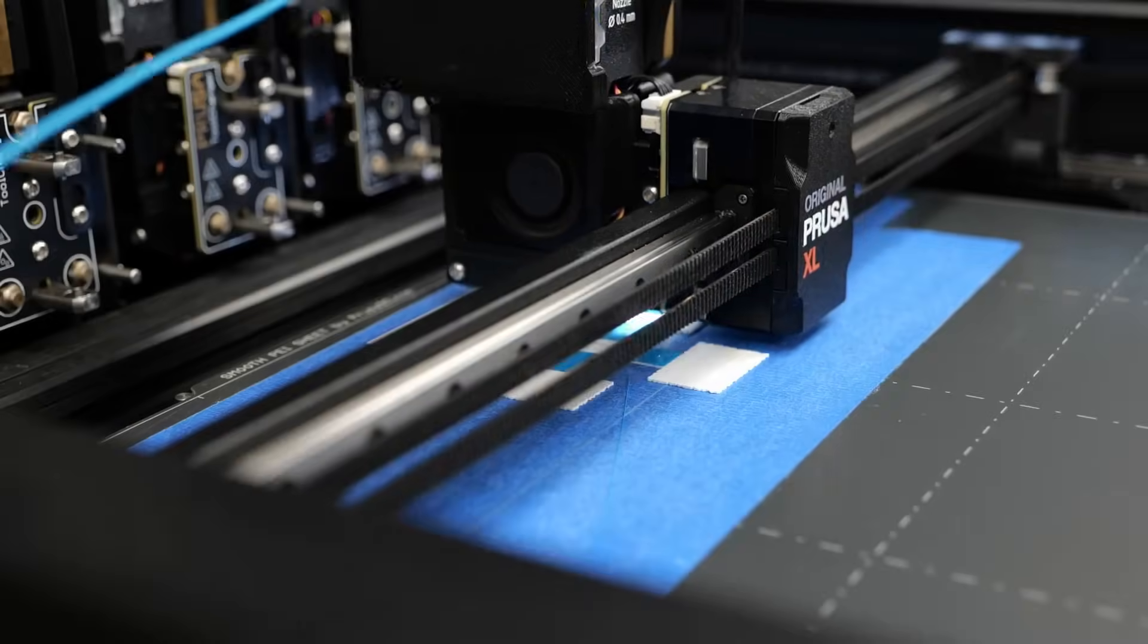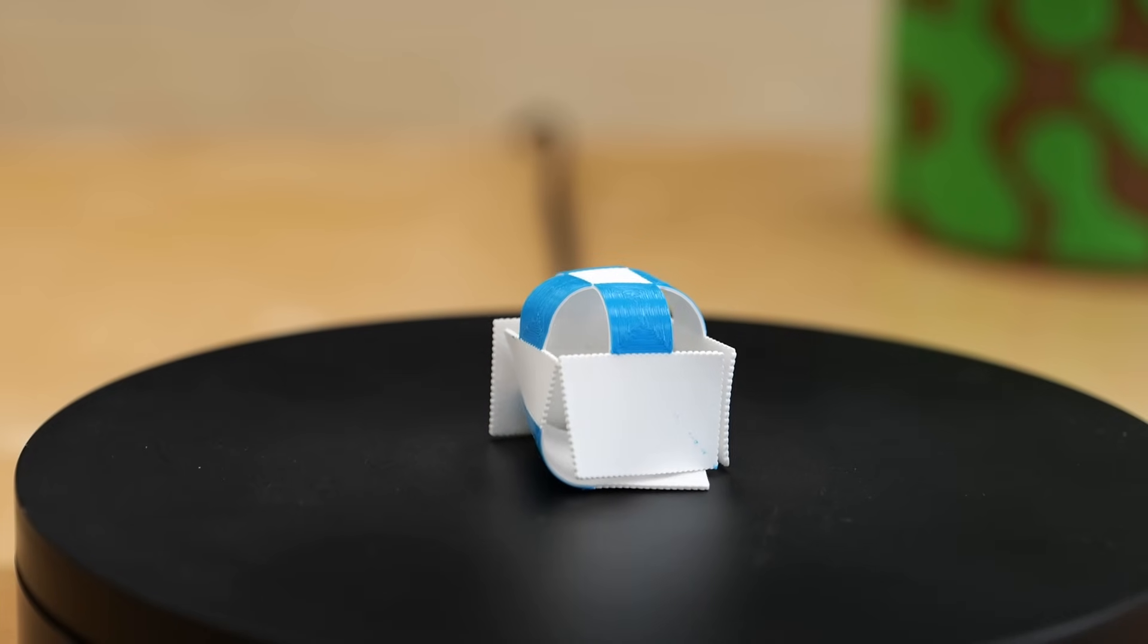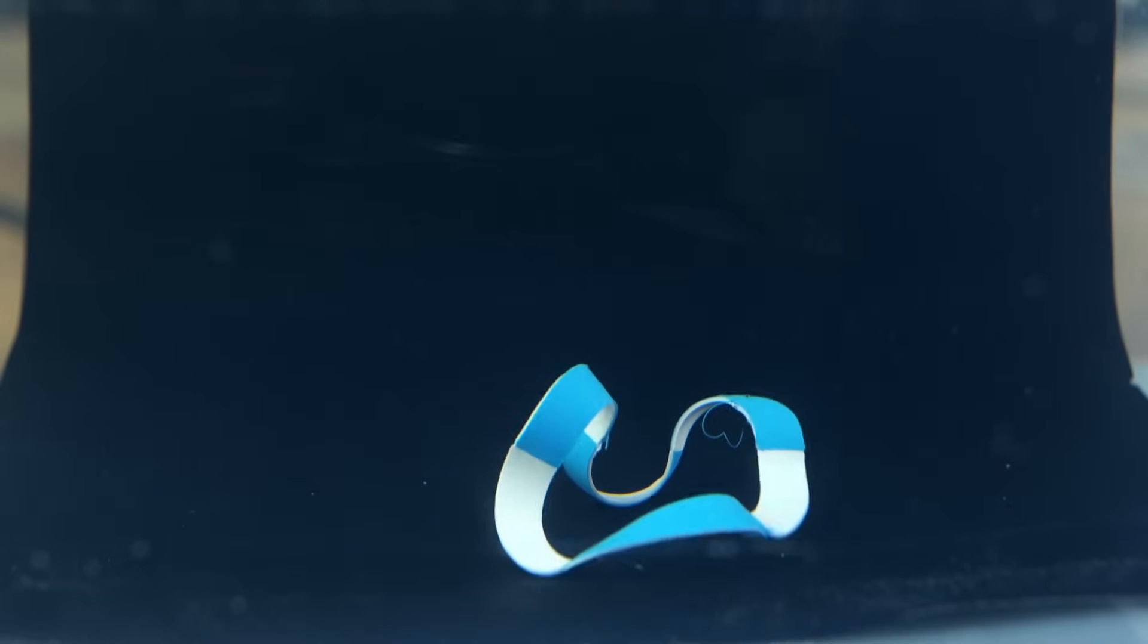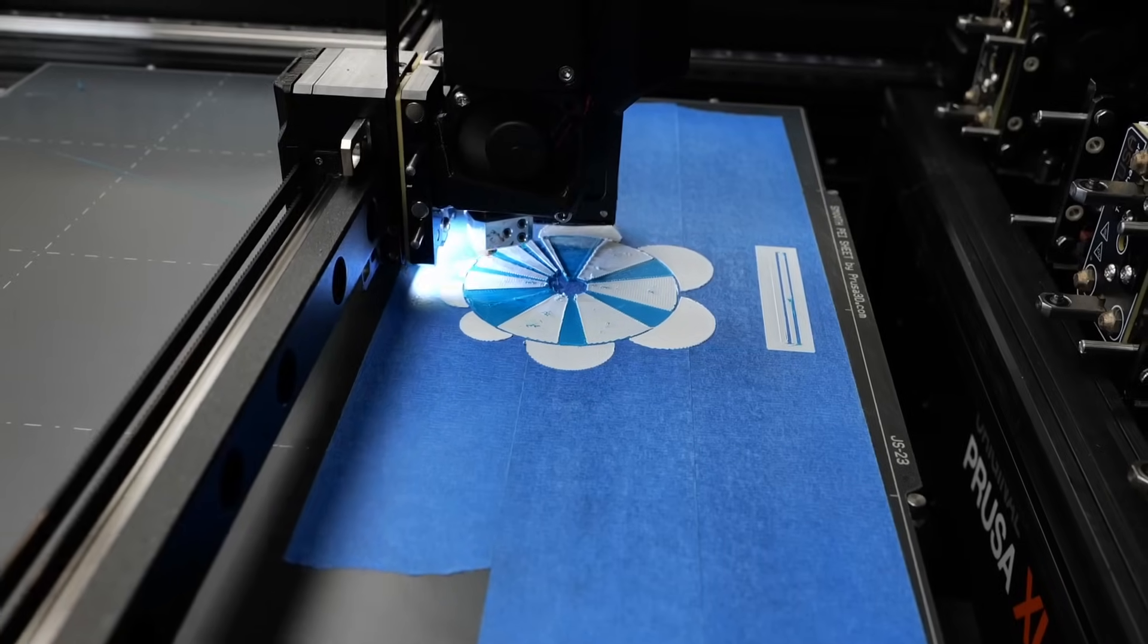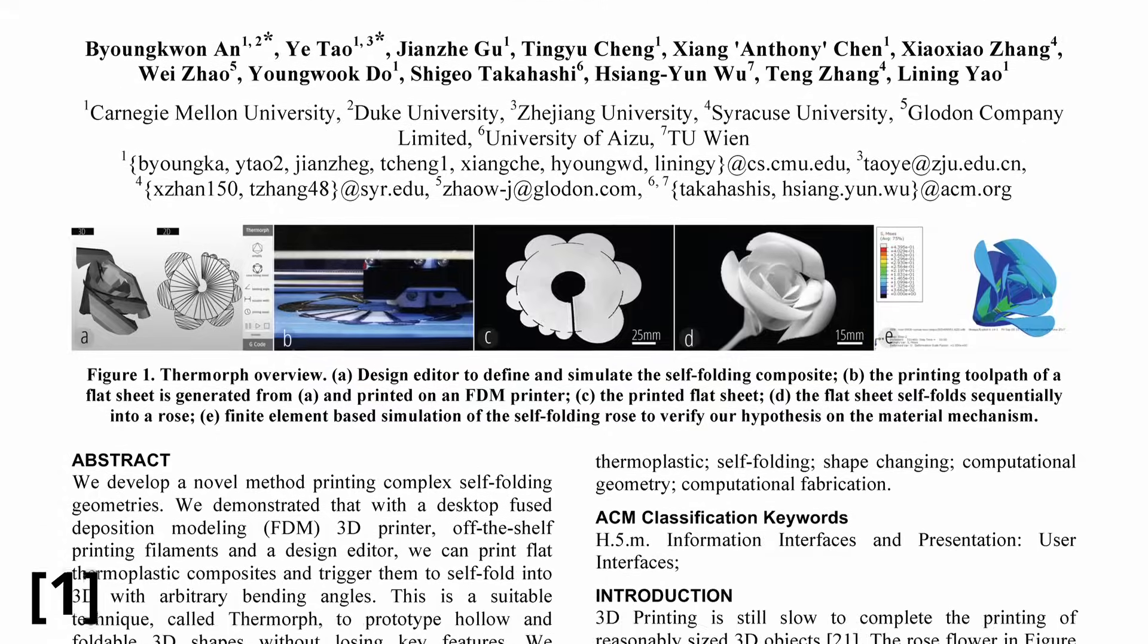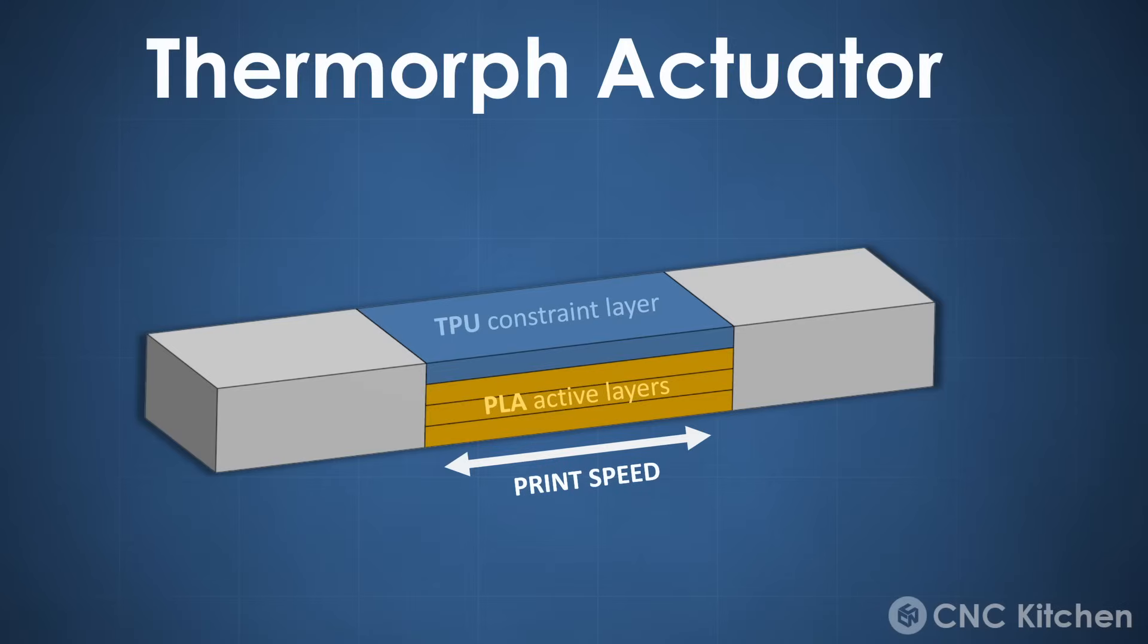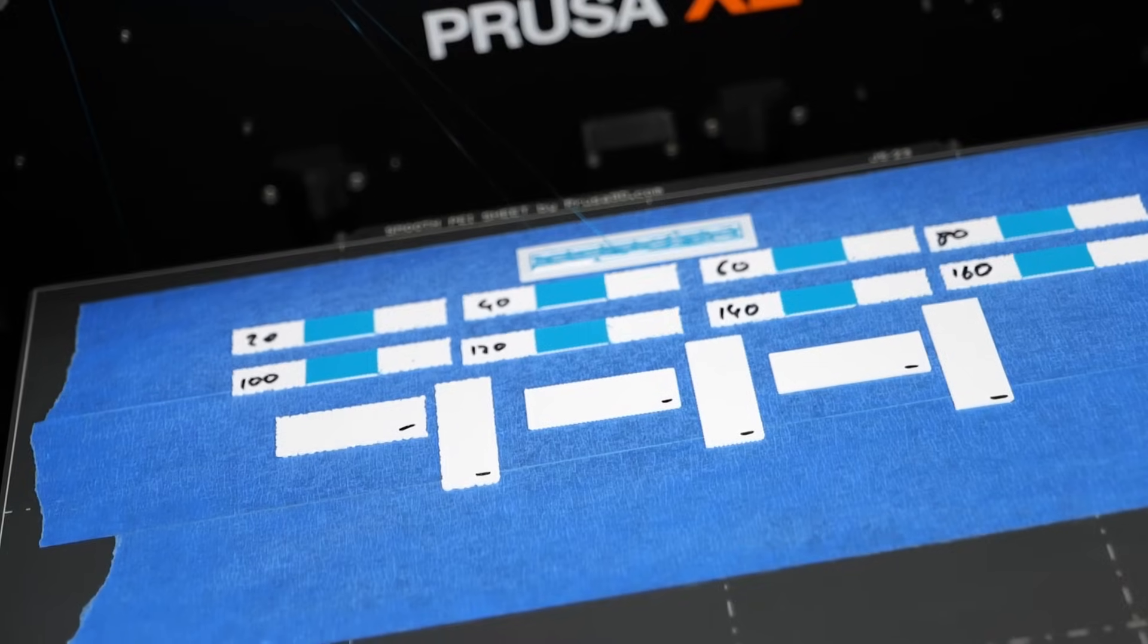Okay, back to the Thermorphs. To achieve the desired shape of the first parts that we printed, we primarily controlled the layer stackup to determine whether we were producing concave or convex parts. The printing angle dictated the direction of the bend. However, this process felt somewhat random and lacked precise control. To make this method applicable for more complex shapes, we need to enhance our understanding and control over the bend angle and radius. This is where the beauty of additive manufacturing comes into play. When printing a part, we can adjust numerous parameters that influence not only the appearance of our print but also its properties. This aspect highlights the novelty of the work presented in this paper. The amount of bending primarily depends on the internal stresses present in our 3D printed part. The primary way to control these internal stresses is by varying the printing speed. The faster we print, the more violently the polymer chains get stretched and the less time they have to relax again, leading to higher residual stresses in the part.